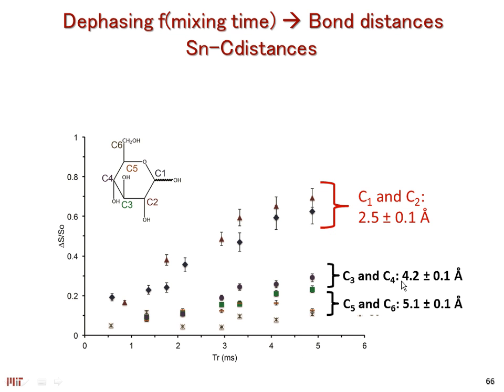So in this respect, for example, we can measure with these REDOR experiments very well the distances between specific carbons when we label our sugars or we label our reactants, with, for example, the tin center. So we know how far away these ones are, what is in close proximity and what is not to the active site, and we can start piecing together, more or less, under reaction conditions, we can heat this up, what is happening dynamically around the active site.